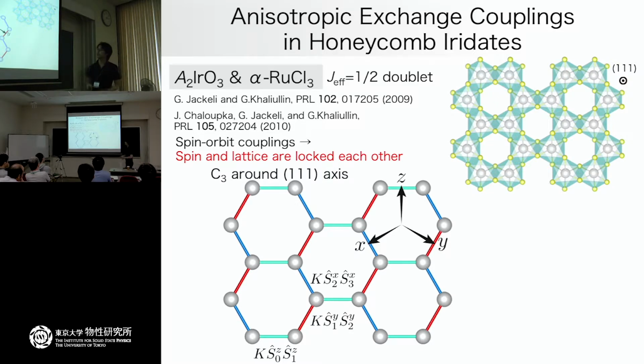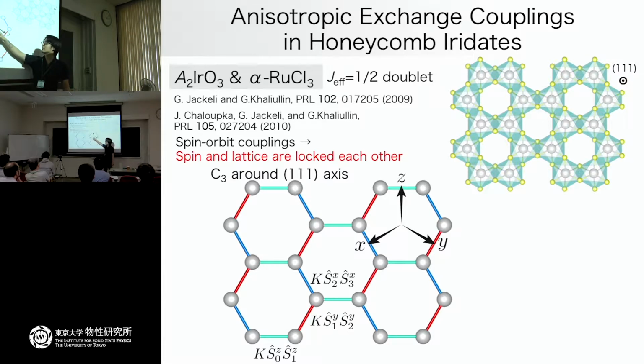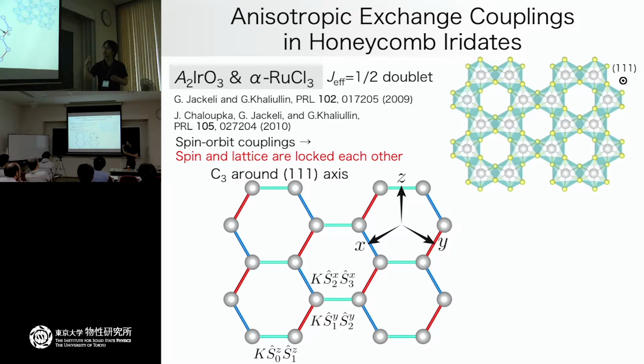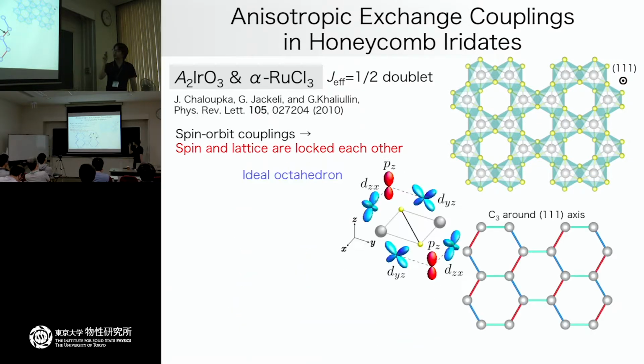First of all, if you have spin and lattice locking, then you can think about lattice rotation. For example, if you put the Cartesian axes like this, where this x-axis is perpendicular to this bond, this y-axis is perpendicular to this bond, and this z-axis is perpendicular to this horizontal bond, then if you rotate your system around the 111 axis, you can make an exact mapping from these to these, and vice versa, simultaneously. So in this sense, this kind of anisotropic interaction is really compatible with your lattice structure, if you have spin-orbit coupling and spin lattice locking due to this relativistic effect.